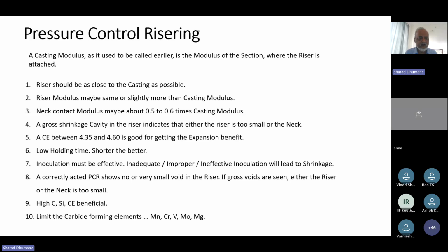So you analyze your holding conditions, your holding practice, your holding time, and then you realize that yes, there is a lot of holding, and whenever there is holding much beyond a certain time, your melt quality gets affected, and you not only get shrinkage defects, you also get some other defects. Holding increases the liquid slag in the metal, and when you do inoculation and treatment, the liquid slag also reacts with the inoculant or the treatment alloy, and reduces the effectiveness of inoculation or treatment. So holding is a major killer of casting quality, a major influencer as far as casting shrinkage defects are concerned in ductile iron.